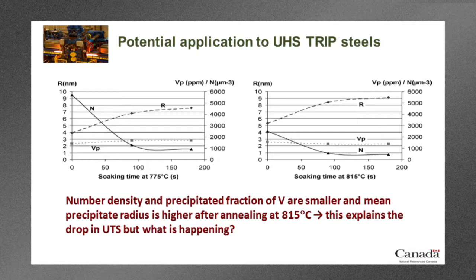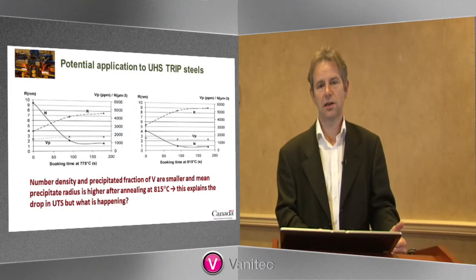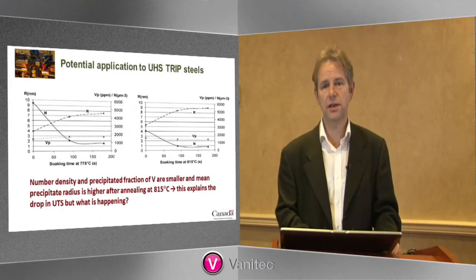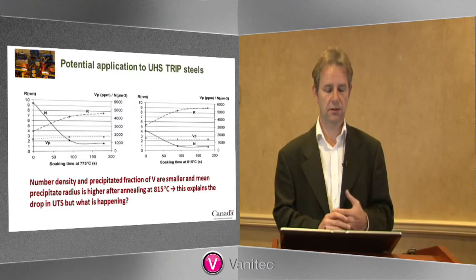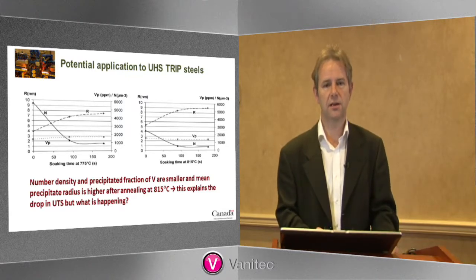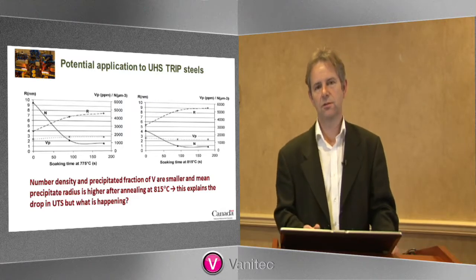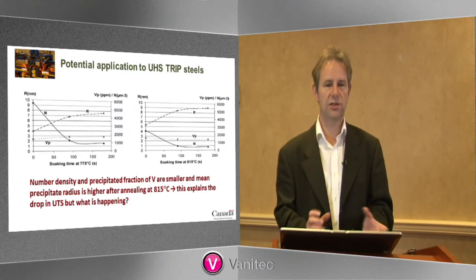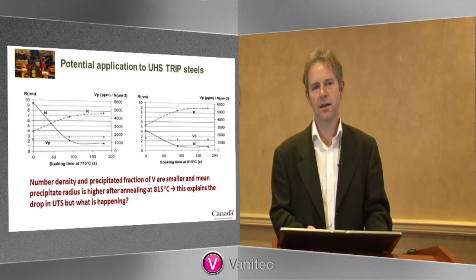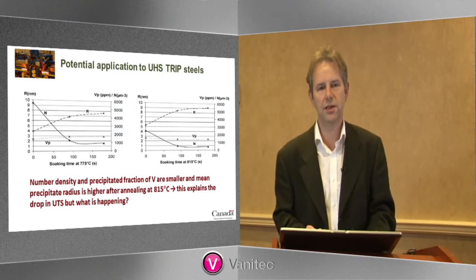So these data show why this particular annealing condition results in a lower ultimate tensile strength than the one on the right-hand side. We have less precipitates globally, and we have a higher radius of those precipitates, so they're less effective at strengthening. Now this is a global picture. Inside the intercritical region, we are in a two-phase region. We have ferrite and we have austenite. And this picture doesn't tell us what's happening in both of those phases.